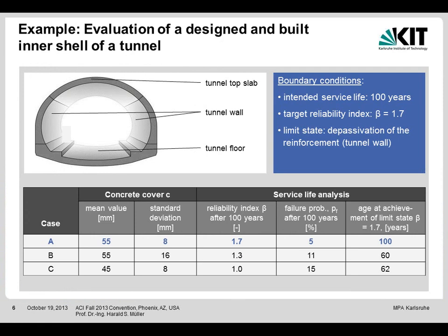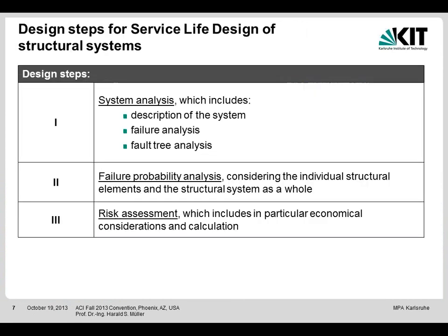Or on the other hand, if there is a misunderstanding, for example, you have just a mean value of 45 instead of 55 millimeter concrete cover, but you have the good execution with the same standard deviation, you end up due to this difference at 62 years. This indicates very clearly how sensitive the calculations can be with this new type of method. You don't waste material if you apply these methods. This is just a simple example to make clear what is the power.